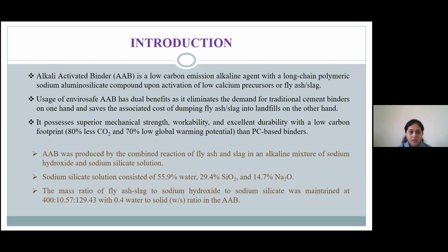So what have we done in this study? We have proposed a novel additive, alkali activated binder, which is a low carbon emission alkaline agent. It has got a long chain polymeric sodium aluminum silicate compound when we activate the low calcium precursors, the fly ash or slag. Now, this alkali activated binder eliminates the demand for use of traditional binders like cement. At the same time, it saves the cost for dumping. Also, it provides excellent durability with a low carbon footprint.